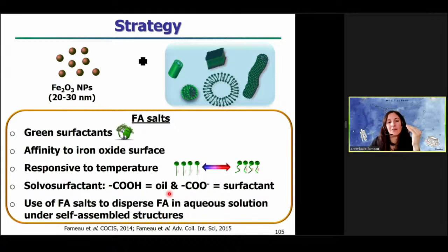So they can be the second immiscible liquid inside the water to wet the surface of the particles and form the capillary bridges. And when you just use the fatty acid in the ionized state, you have the surfactant properties of the fatty acid. And so if you use, as I showed you previously, fatty acid assemblies with fatty acid under carboxylic form and carboxylate form, you can vehiculate the carboxylic form to form the capillary bridges.